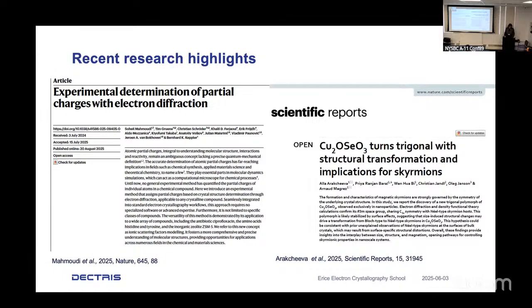This is another example. This was done with the ELDICO machine, so with a Quattro and the group. They've been looking at the structural difference between nanocrystals and bulk crystals with X-rays and nanocrystals with ED. And in these copper oxyselenide, they found a new trigonal structure that has implications for skyrmions, and so they speculate about the effect of the surface on the structure and the magnetic properties. So that's quite interesting to see how crystalline properties change just with the size of the crystal.